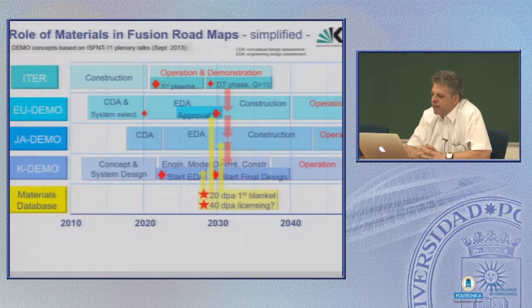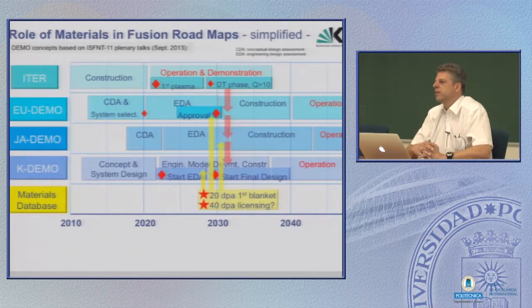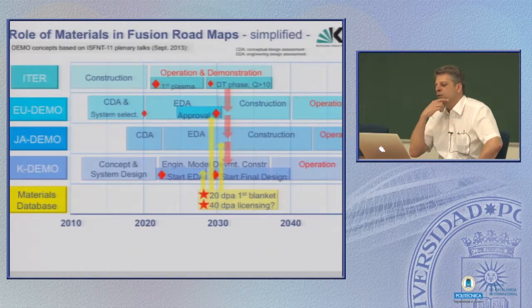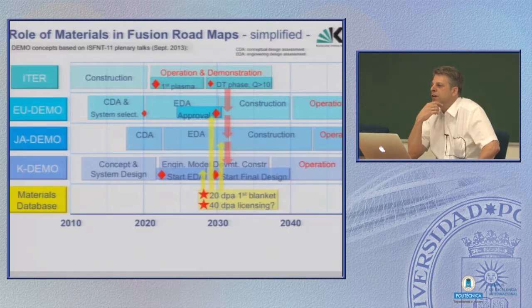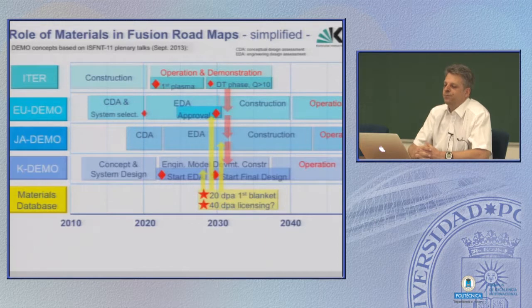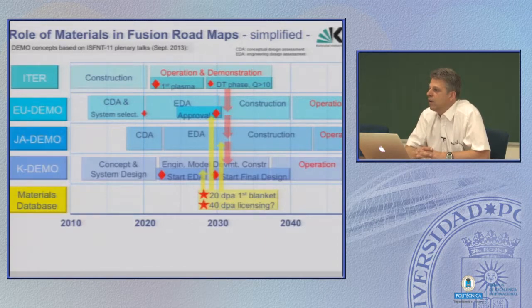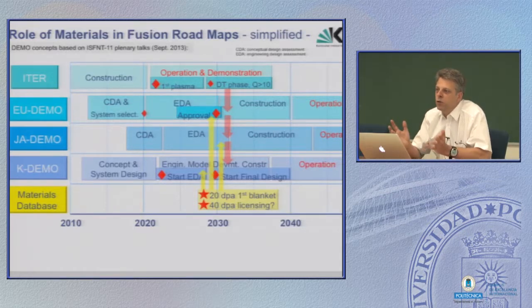And if you remember what I told you yesterday about defects in steel, you might wonder why ITER is fully built of only one steel, this austenitic steel. And if you remember, I have shown you austenitic steels are rather prone to swelling. But in ITER, this is not an issue, because ITER will produce so few neutrons that the dose level inside ITER will be only about 1 to 2 dpa at some single points in the whole lifetime of 20 years. So neutron irradiation is almost no issue in ITER, and that's why it can be built from available standard material like the 316 steel.